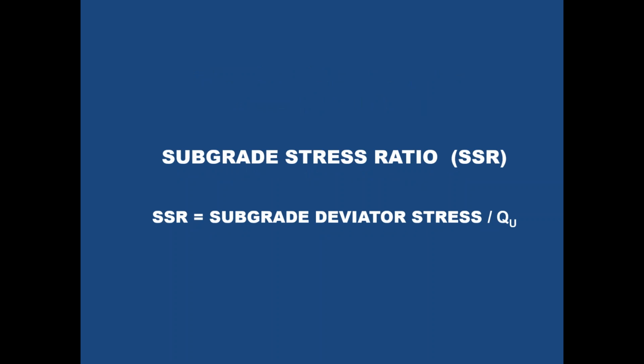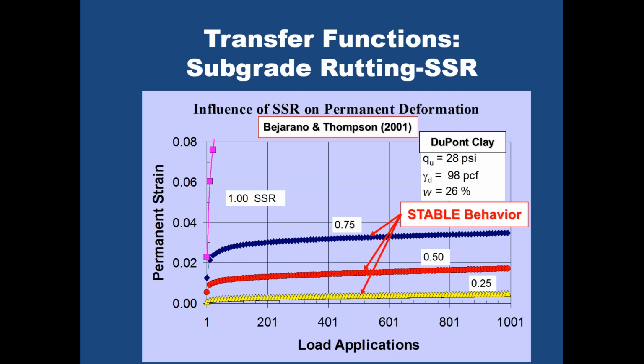Okay, subgrade stress ratio, where we're looking at subgrade deviator stress divided by strength. This is work that Bejarano and I did back in the early 2000s for the FAA Tech Center accelerated loading scheme. We were looking at a bunch of soils, and we found that subgrade stress ratio was obviously related to the development of permanent strain in a subgrade. And as you can see, this is lab data. We've got the DuPont clay here in this case. If you're at low stress states, you don't get much strain. If you go to 0.5, you get some, 0.75 more. And obviously, if you're loaded to 100% of its strength, you're going to get a considerable amount of permanent deformation. That one obviously is unstable.